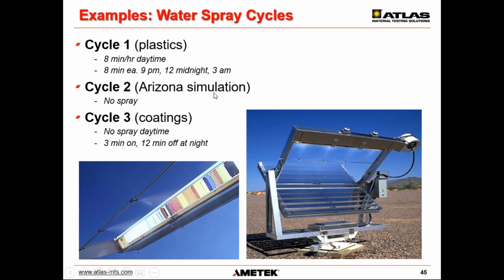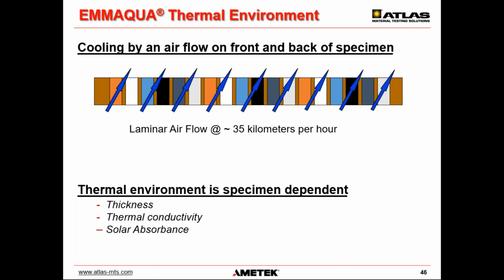Cycle 2, which is an Arizona simulation, since we don't see a lot of rain there, is no spray at all. And then cycle 3, which is primarily for coatings, to simulate that dew formation that you see every night in Florida, we spray the samples for 3 minutes and then off for 12 minutes, and that keeps the samples continuously wet during the course of the nighttime hours. And so those are the sprays that are done in the spray cycles that are referenced in these ASTM G90